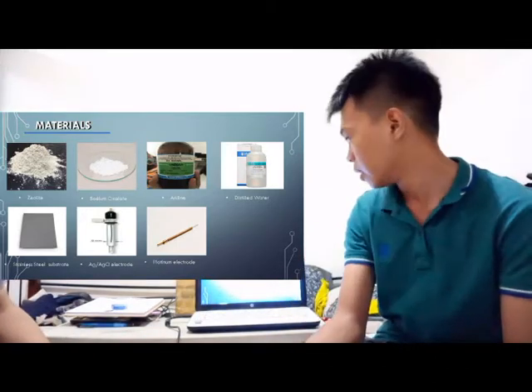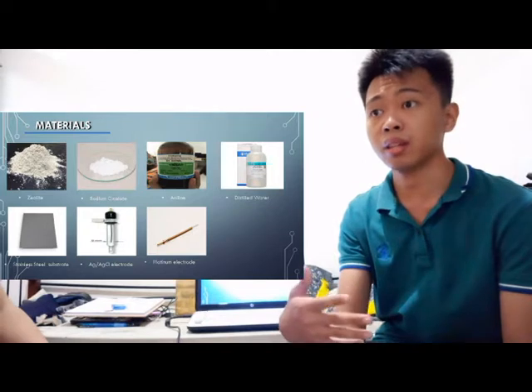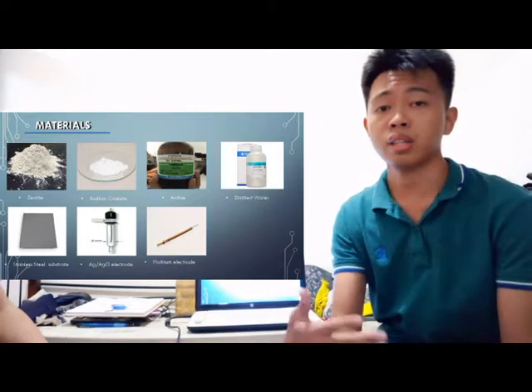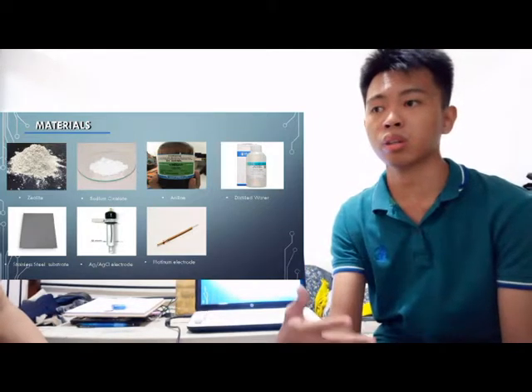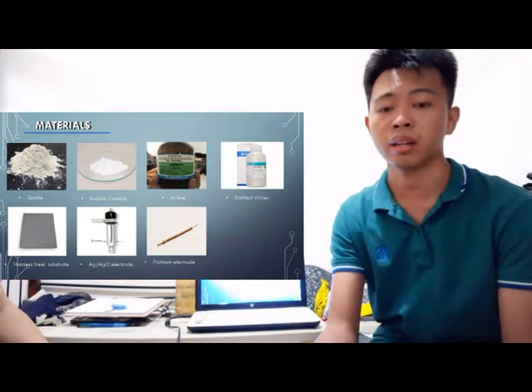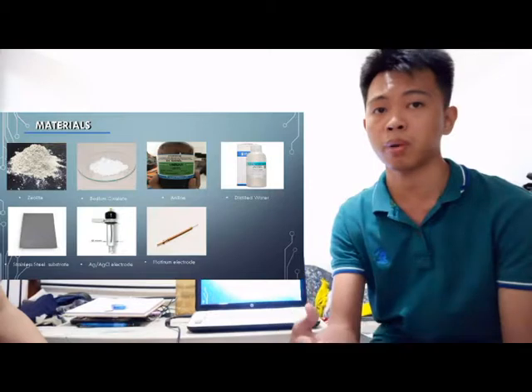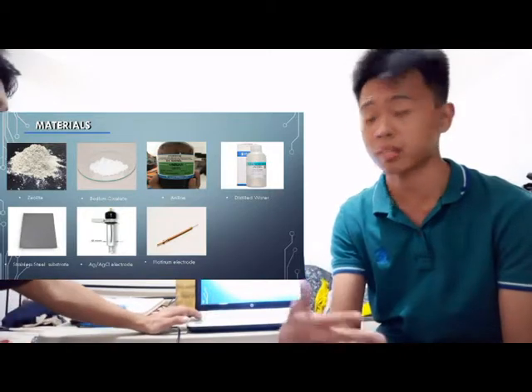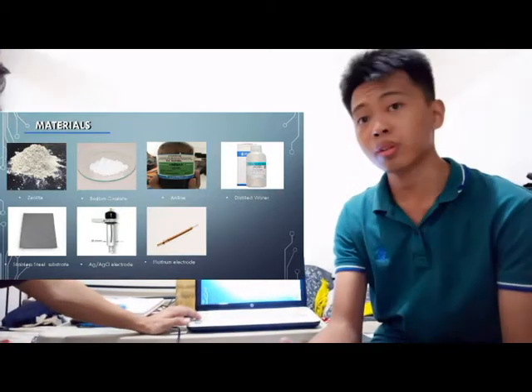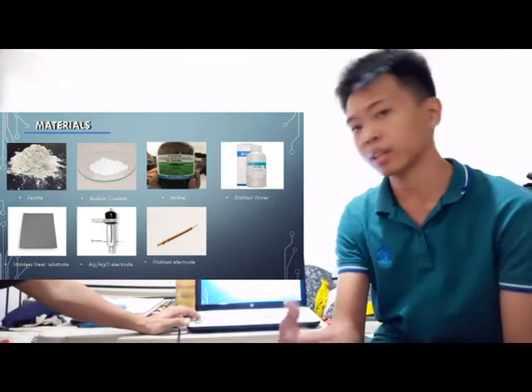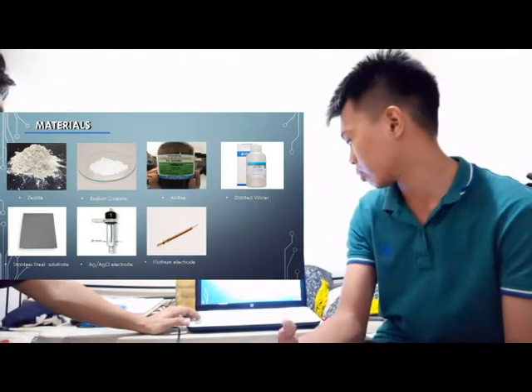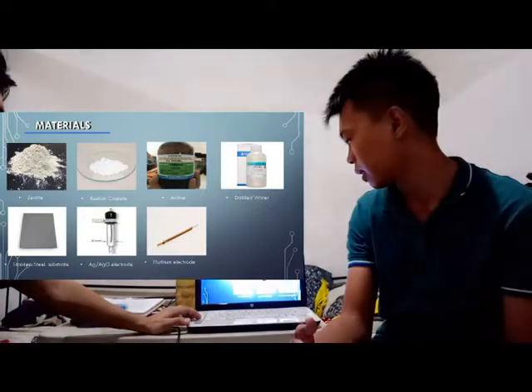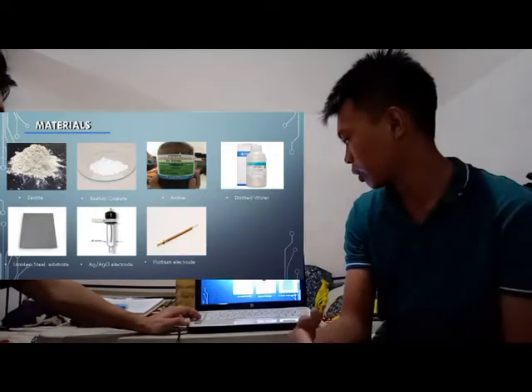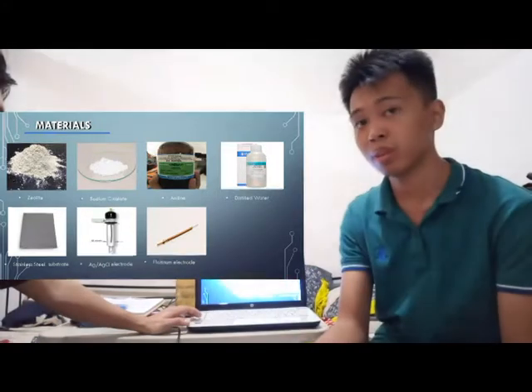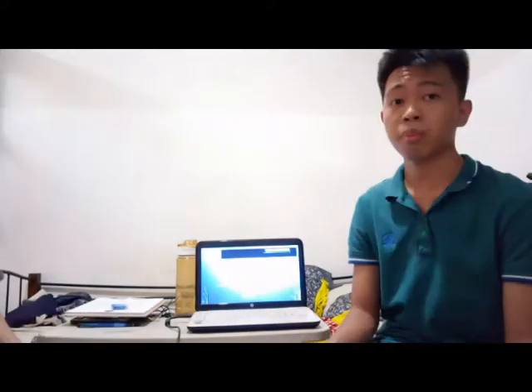So for the materials used in our experiment, we use zeolite and aniline as the main components of our material. The sodium oxalate is used as an initiator, and during electrodeposition, it will act as a barrier to prevent the dissolution of stainless steel. We also use DI water as a cleaning agent, and three electrodes: the stainless steel substrate, AgCl electrode, and platinum electrode.